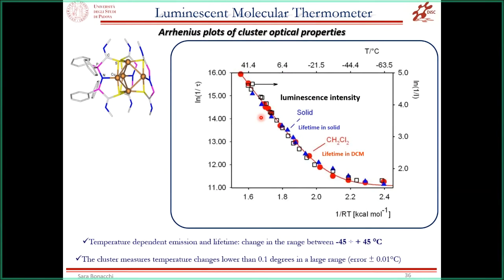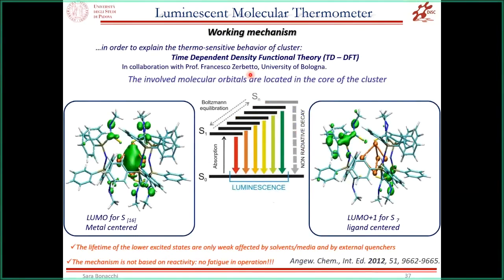This is not the end of the story, because we also tried to understand the origin of this peculiar behavior, so we performed time-dependent density functional theory, and we observed that the LUMO is metal centered, but the LUMO+1 is more ligand centered. This explains why at low temperature there is a very fast Boltzmann equilibrium among different excited states, but as soon as we increase the temperature, we populate a non-radiative excited state, which explains why at room temperature we have a cluster with a very low quantum yield and a short lifetime.